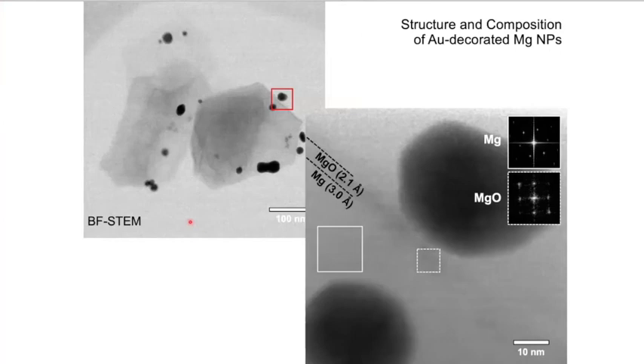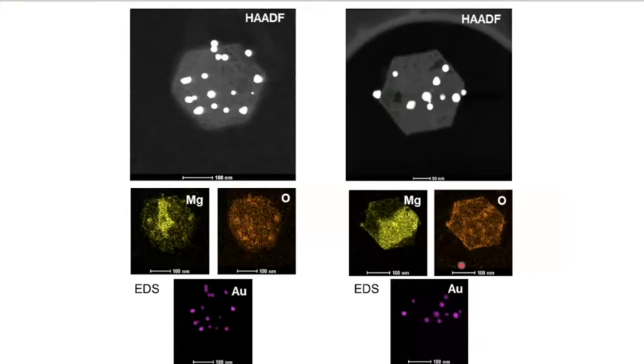But we manage, and one of the ways we manage is by using a bright field STEM where the magnesium here has more interaction with the beam, we're able to look at the oxide layer, for instance. And funny enough, the oxide layer appears to reform between the gold particle and the magnesium metallic core. We don't yet fully understand the mechanism of this galvanic replacement due to that oxide layer, but we are working on that, and it's very exciting. They are gold, okay? We can do all sorts of experiments, such as energy dispersive X-ray spectroscopy.